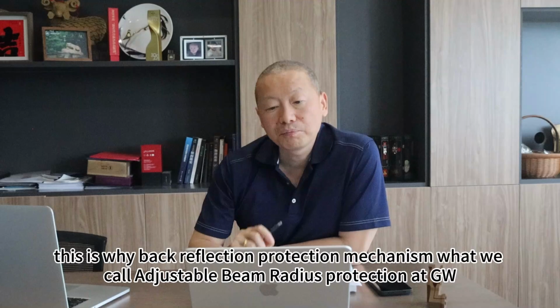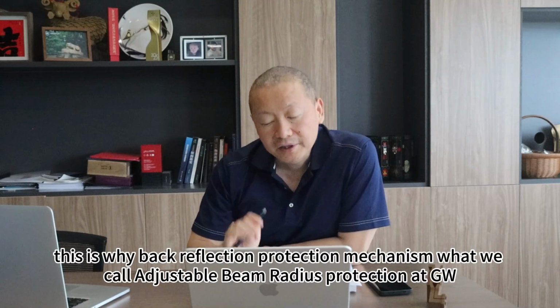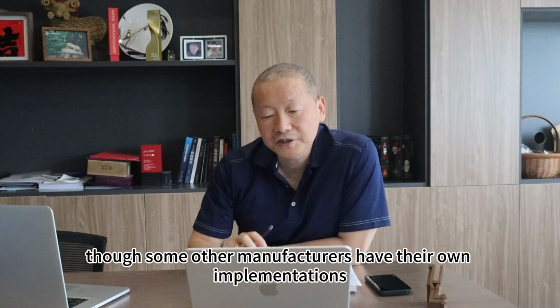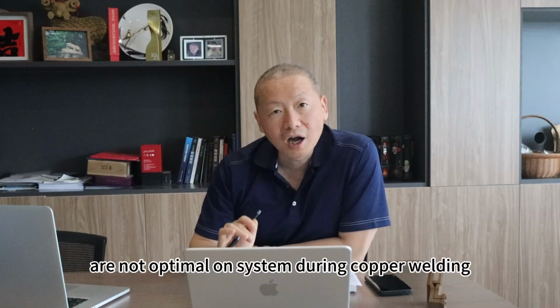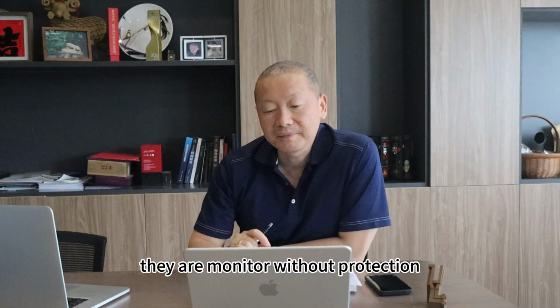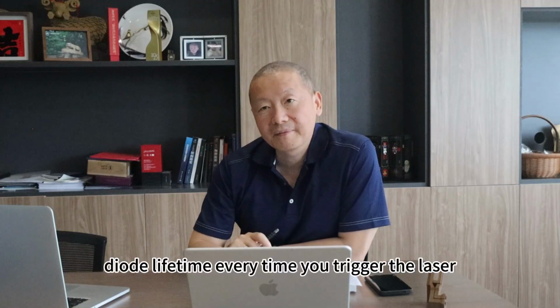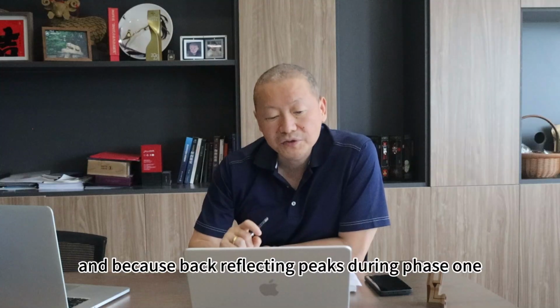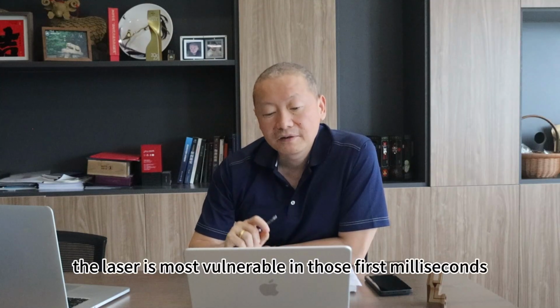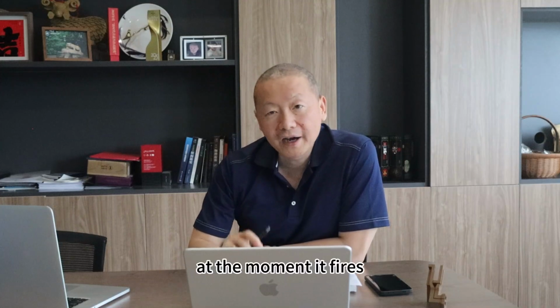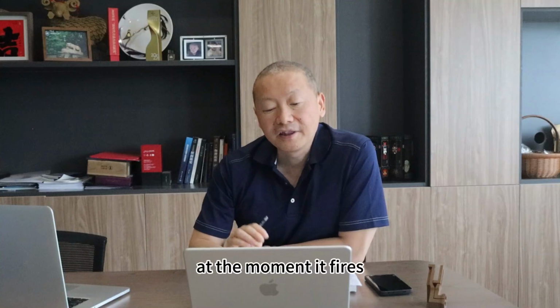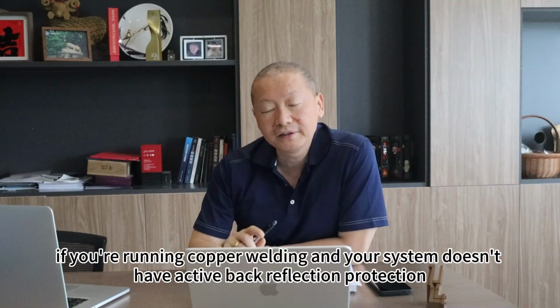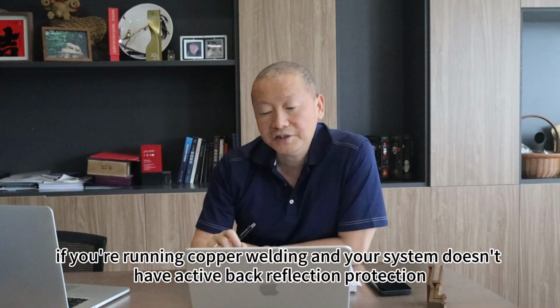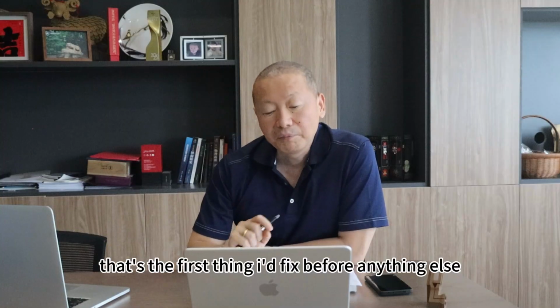This is why back reflection protection mechanisms, what we call Adjustable Beam Radius protection at GW, though some other manufacturers have their own implementations, are not optional on a system doing copper welding. They are mandatory. Without protection, you are rolling the dice on your diode lifetime every time you trigger the laser. And because back reflection peaks during phase 1, the laser is most vulnerable in those first milliseconds, at the moment it fires, not during the steady state weld. At the moment it fires. If you are running copper welding and your system doesn't have active back reflection protection, that's the first thing I'd fix before anything else.